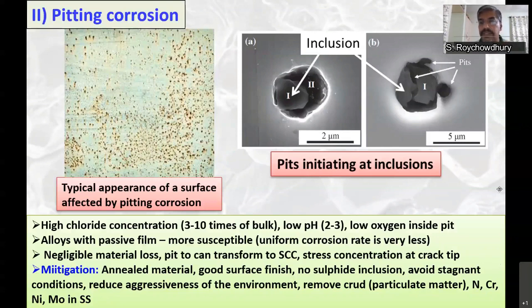So that will again increase your propensity of pitting. Avoid stagnant conditions. As I told before, stagnancy will promote this pit growth. Reduce aggressiveness of the environment, remove crud. If you have particulate matter in a flowing stream, it will tend to deposit at the 6 o'clock location, and it will promote this stagnancy and pitting corrosion.